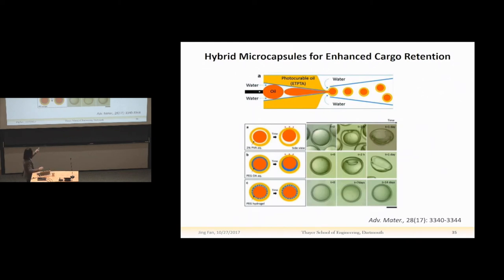And then we tailor the aqueous shell from a PVA solution to a hydrogel solution, and we get a very good encapsulation efficiency by using a hydrogel and polymer hybrid shell. By this, we realize the encapsulation of highly volatile pinene within these capsules for over 14 days, which is very challenging using traditional double emulsion templated capsules.